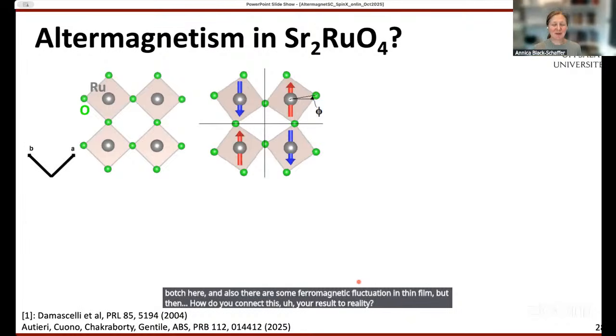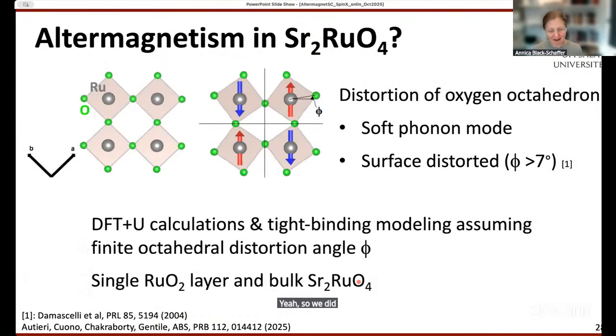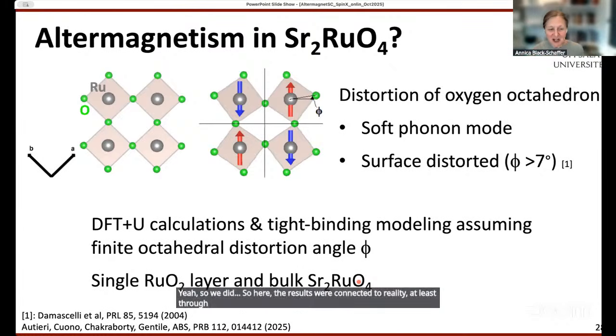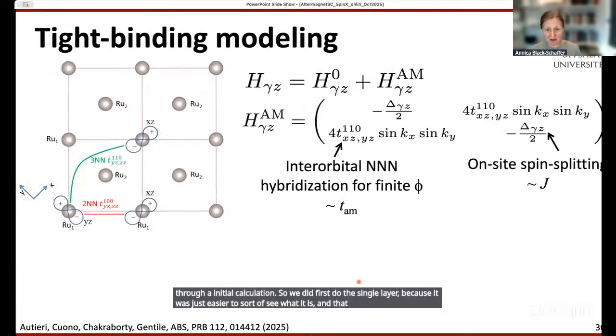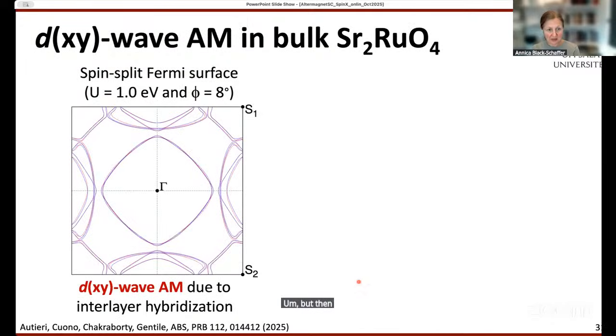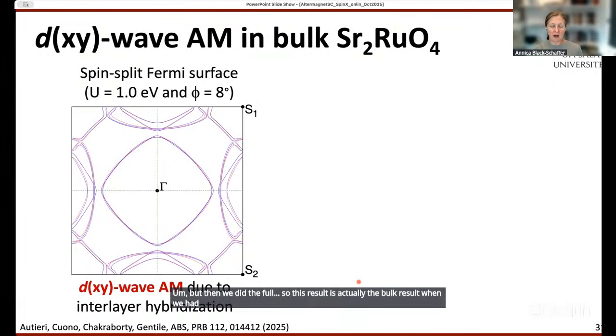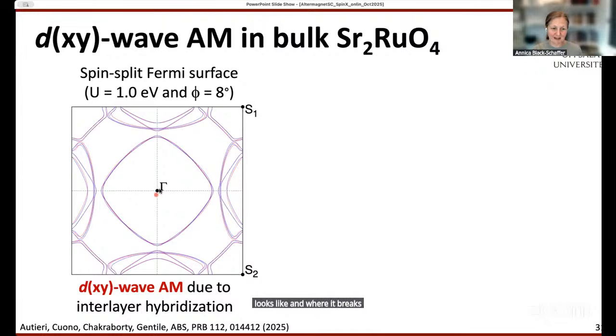Yeah. So here the results were connected to reality, at least through ab initio calculation. We first did the single layer because it was easier to see what it is, and that was how we extracted the band structure. But then we did the full structure, so this result is actually the bulk result. I didn't have it in the talk here, but we did extract what the interlayer hybridization looks like and why it breaks the symmetry.